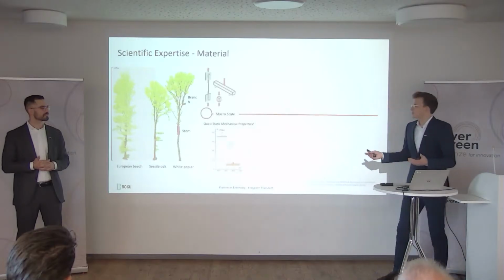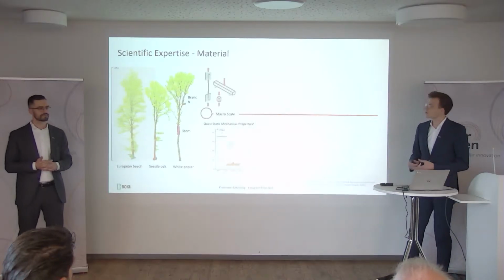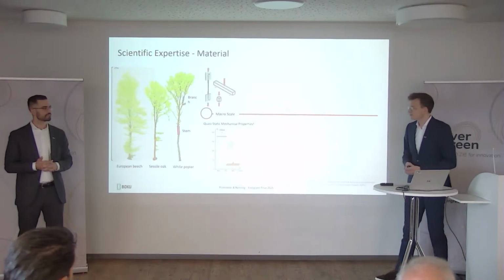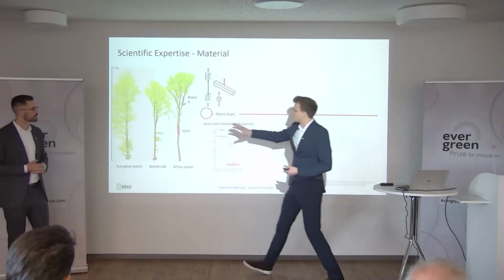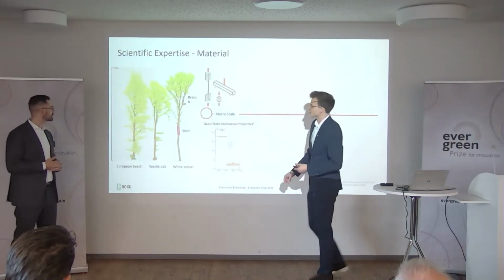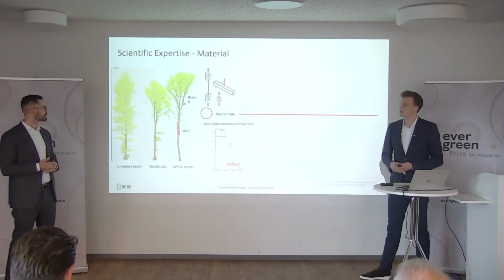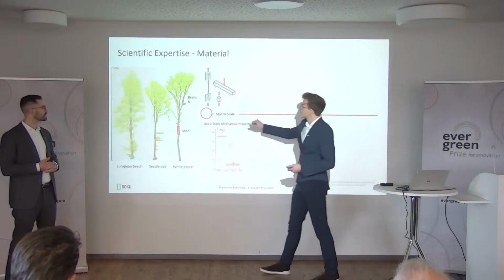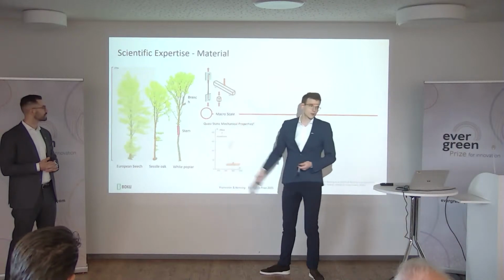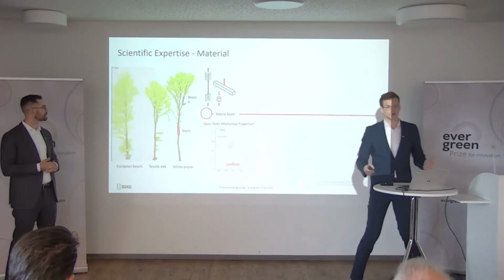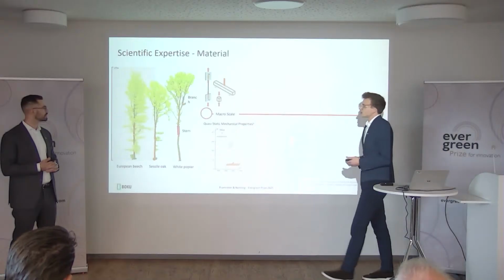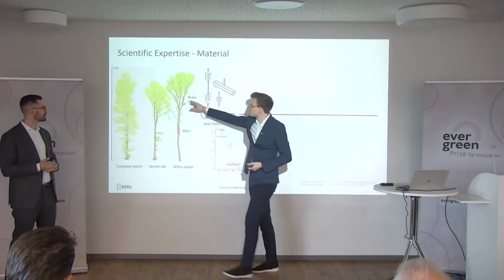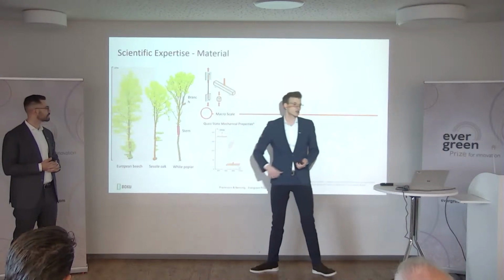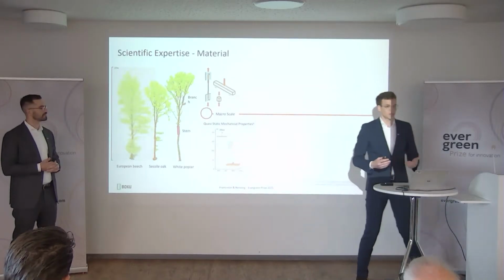We teamed up with the Institute of Forest Growth at BOKU. We did some 3D laser scanning, and so we captured the full tree in a digital model. And this made it possible to trace back the different tensile, compression, and three-point bending samples into the standing tree. And that allowed us to find out, for example, that a steep branch does differ from a flat branch in terms of mechanical properties.